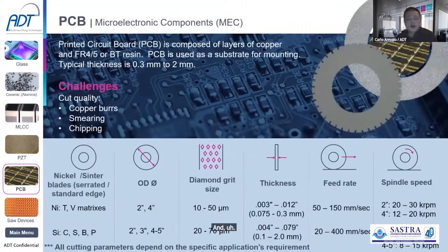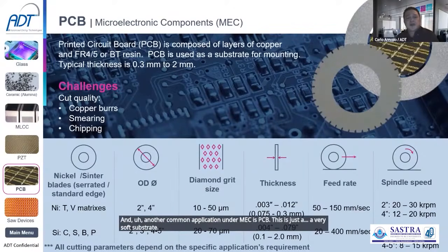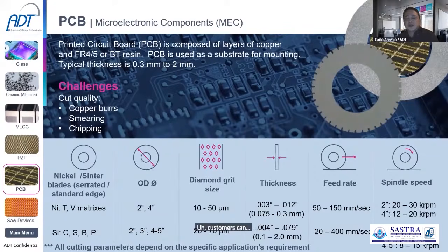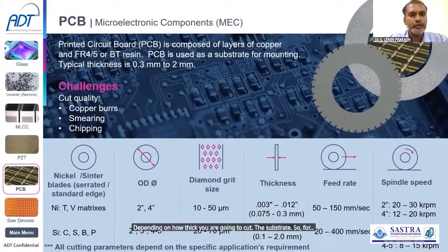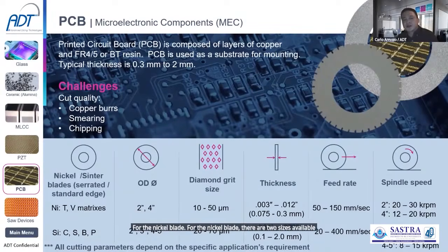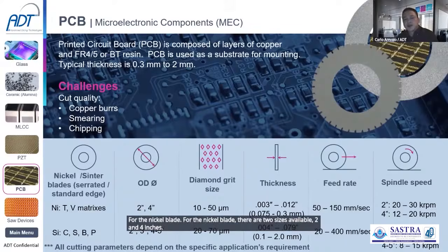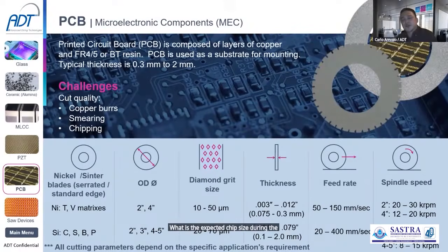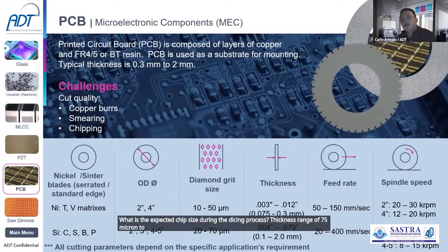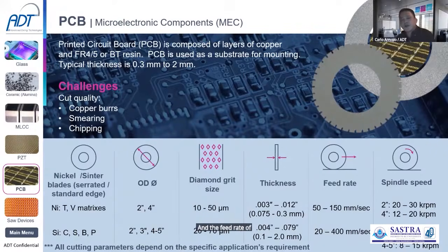Another common application under MEC is PCB. This is just a very soft substrate. The market can use a nickel blade or a sintered blade, depending on how thick the substrate you are going to cut. For the nickel blade, there are two sizes available, 2 and 4 inches. The diamond grit size would range from 10 to 50 micron, depending on the expected chip size during the dicing process. Thickness range is 75 to 300 micron, and the feed rate is 50 to 150 millimeter per second.